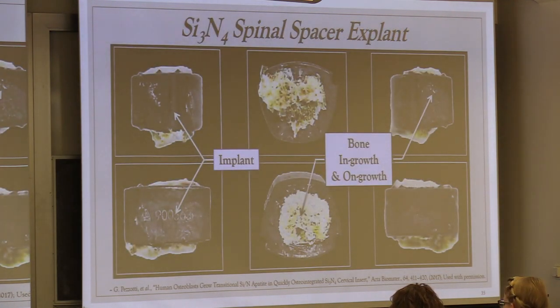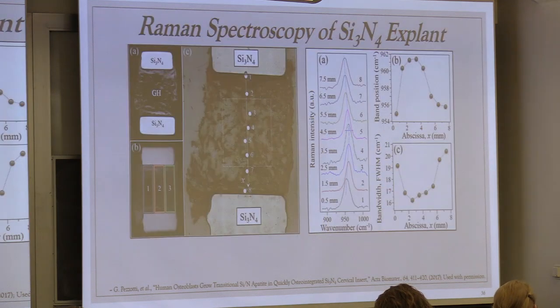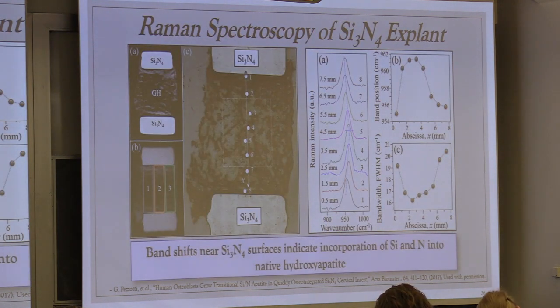This is what the explant looked like of the silicon nitride in the cervical. You can see that here's the implant itself, and this is what's called the graft hole, where bone is grown in and through the center hole of the implant. And there was also some bone on-growth that was actually noted as well. And what we looked at using XPS and Raman spectroscopy is the change in the hydroxyapatite, and this is in the center of the implant.